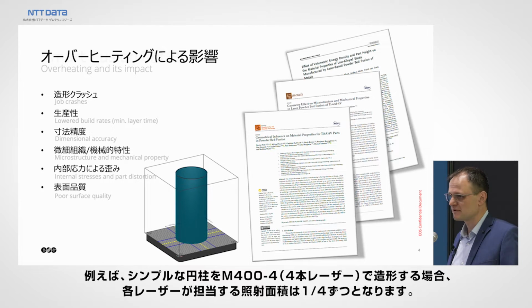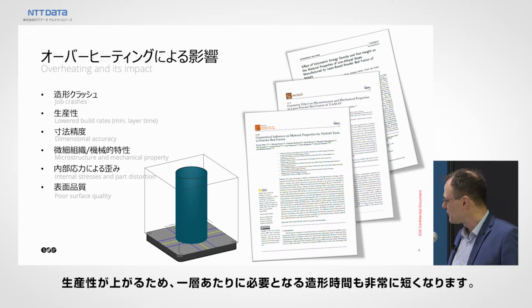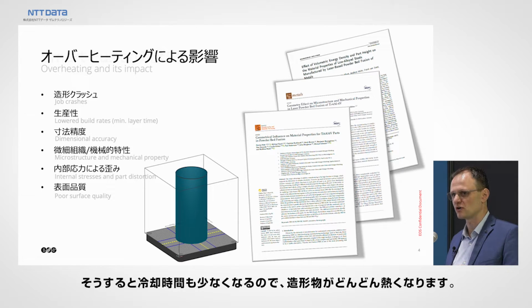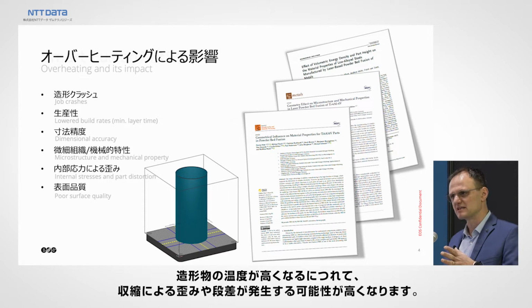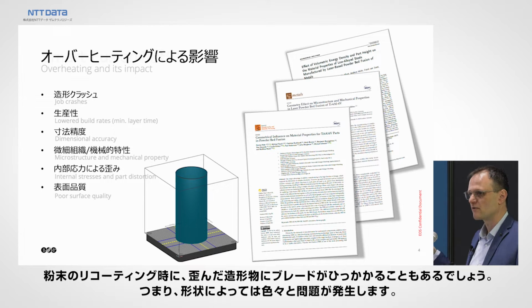As an example, something as simple as a cylinder printed on an M400-4 with 4 lasers can be a very good representation of this. If you have very little material being molten per laser, that means you have a very short layer time. That means your part is getting hotter and hotter. And whilst it is getting hotter, the part is moving with regards to dimension. It is shrinking. It can have shrink lines. The recoating can get very rough so that your recoater blade catches it. So a lot of things can go wrong really with printing one simple geometry such as that.